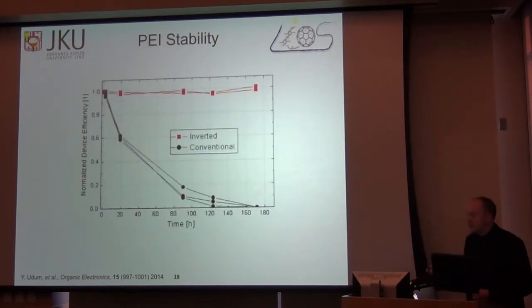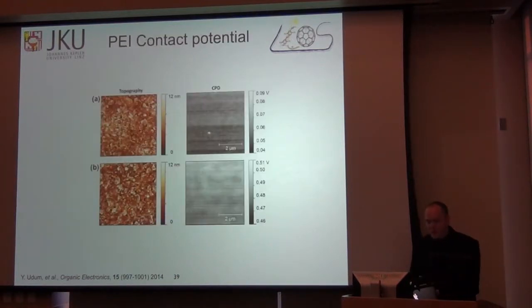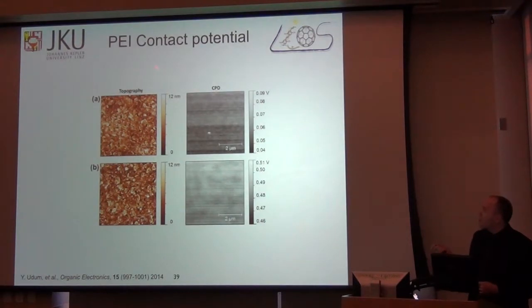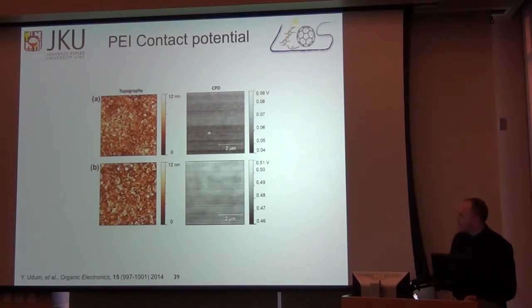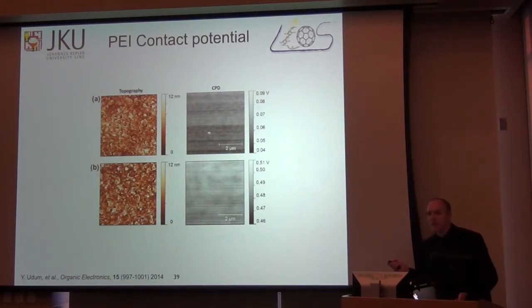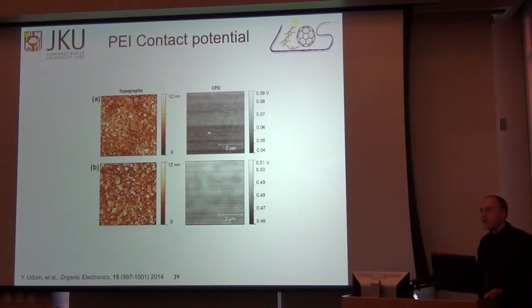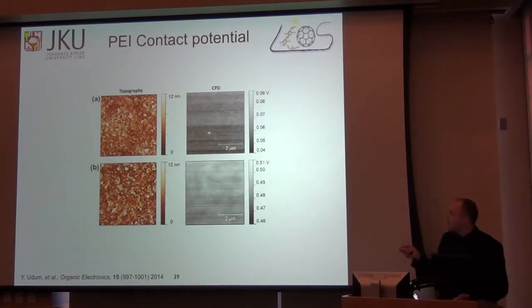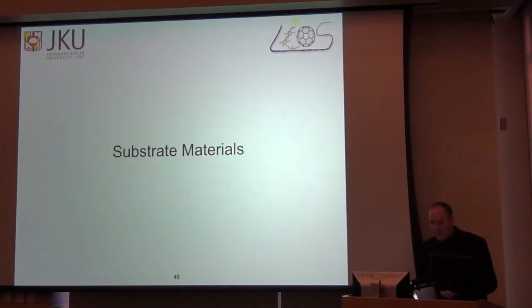These devices with polyethylenimine are similarly much more air stable than their conventional counterparts. And the reason that this works is that the polyethylenimine introduces a contact potential dipole, bringing the effective electron affinity 500 millivolts closer to the vacuum level, making it much easier to add and remove electrons from the LUMO of the fullerene. So you can use this on almost any oxide or metal surface to render it an air-stable electron selective contact.